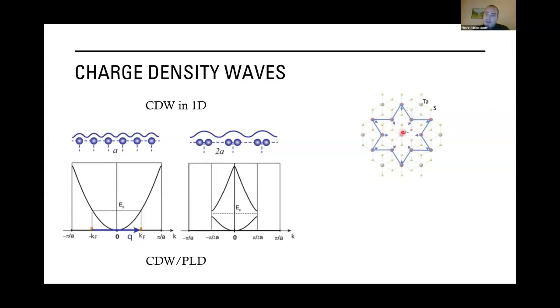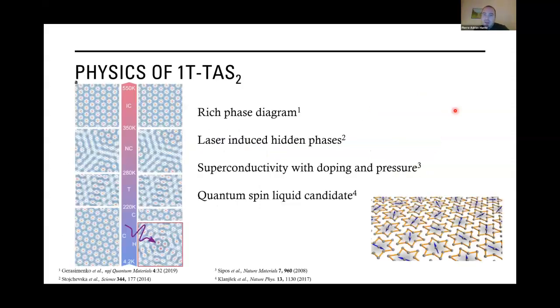And so this single electron in the center will follow the Hubbard model that was described at length in the previous talk. So I will not go too much into detail inside this model, but basically you have a competition between on-site repulsion and hopping. And this will lead at a sufficiently low temperature to the appearance of a Mott insulator. And this Mott insulator is ruling the rich physics of this tantalum disulfide.